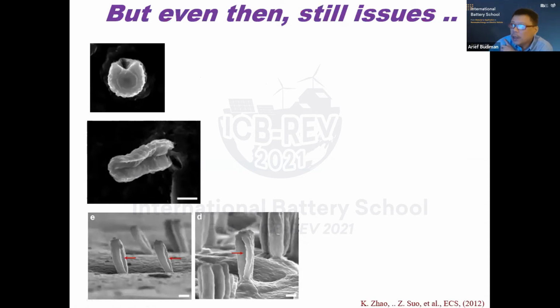But before we got into that, I mentioned just now, silicon nanowire is not without the problem of cracking. It still has the problem of cracking. So we see this, it's a silicon nanowire, which upon some lithiation starts breaking from the outside, as you can see. So you see that the inner core seems to be maintained, but the high tensile stress must be on the outside. You see this, you see that, it all cracked. The crack must be from the outside.